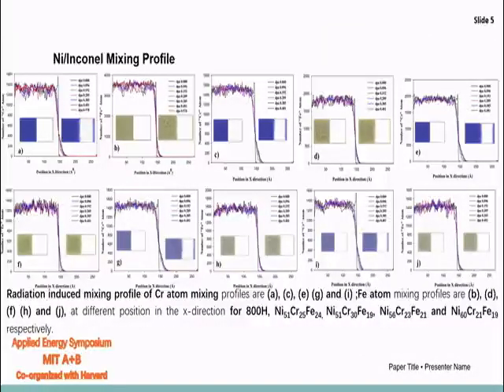In this slide, we have presented the mixing profile at different DPA levels for iron and chromium atoms due to the radiation cascade for 5 different Inconel nickel multimetallic layered composites that we have used in our simulation. If we look closely at those mixing profiles, we can see that the mixing tendency of the chromium is quite higher than the iron atoms. Moreover, this mixing tendency has a very linear dependency with the radiation dose.